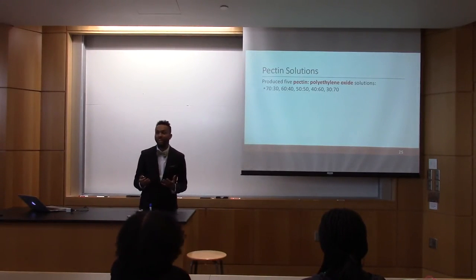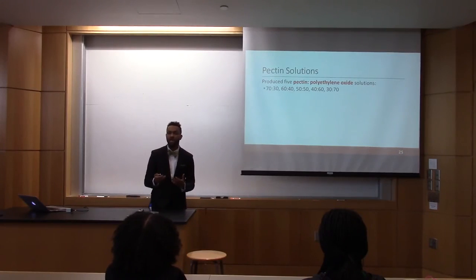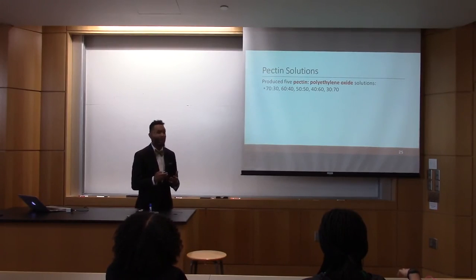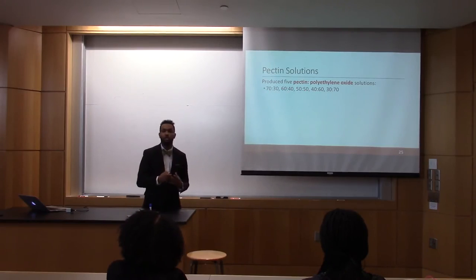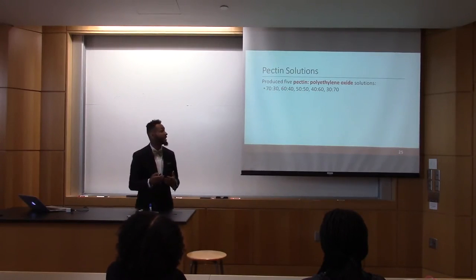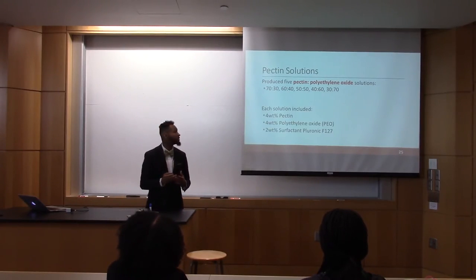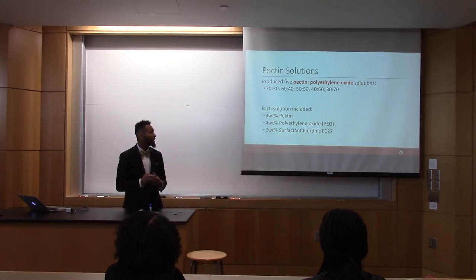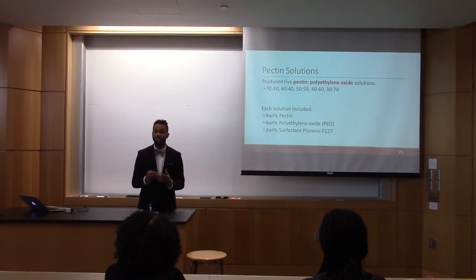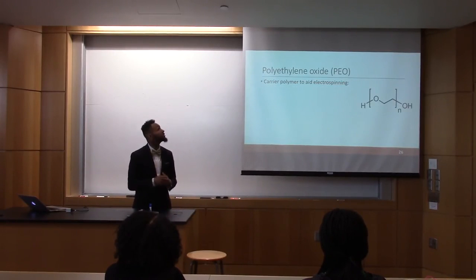So these pectin solutions that I used included producing 5 pectin polyethylene oxide (PEO) solutions. Polyethylene oxide is my carrier polymer. I created different ratios, including 70-30, 60-40, 50-50, 40-60, and 30-70. Each of these solutions included 4% by weight pectin, 4% by weight polyethylene oxide, and 2% by weight surfactant Pluronic F127. We're going to go through each of those ingredients.